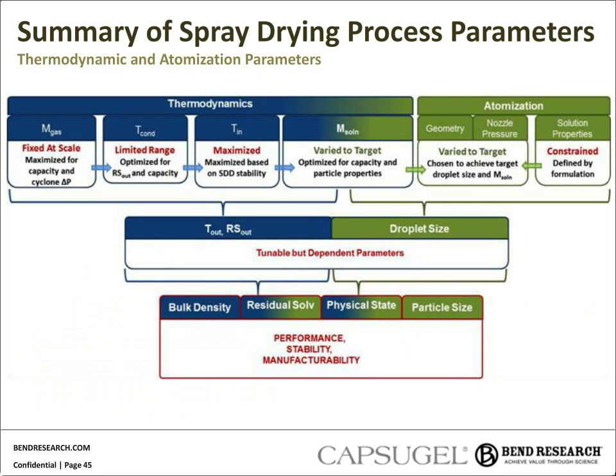So in summary, this chart shows the key spray drying process parameters grouped by those aspects of thermodynamics or droplet drying and atomization or droplet formation. The top row, I won't go through every box, but the top row lists the key independent parameters and briefly summarizes the selection criteria and constraints. And the second row shows the reduced set of dependent parameters like outlet temperature and relative saturation that are often highly correlated to the SDD attributes like density, residual solvent, physical state, and particle size.